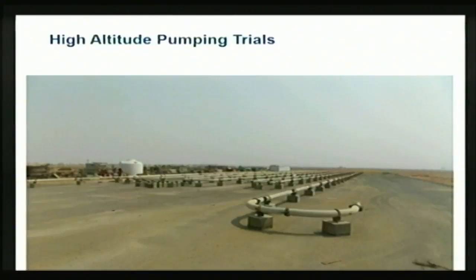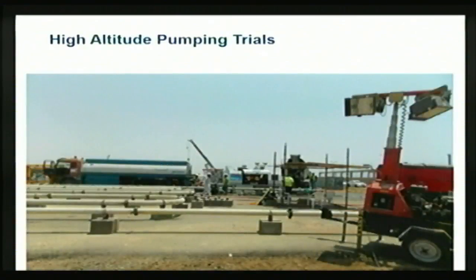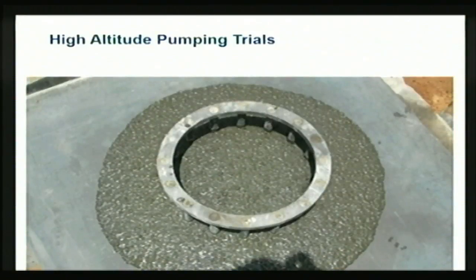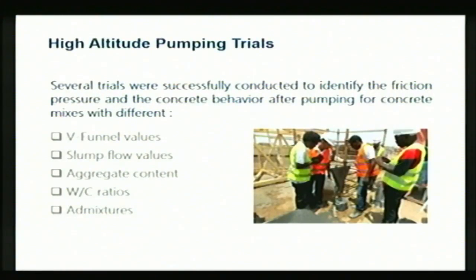Each elbow was 1 bar, each flange was half a bar, and we added that. So we designed that system to simulate even more than 500. This is the 1 kilometer that we did actually. And we did the high altitude pumping trials with the mix design that we finally decided on. And we started checking the J-ring and the stability and the slump flow and the V-funnel. All these were important. And we found out that on a height like this, the V-funnel becomes one of the key elements for pumpability. The V-funnel test becomes the real secret, whether this concrete is going to be pumped so high or not. So anything below 13 seconds was acceptable for us, but we found out that we actually needed 8 seconds to get the mix to reach there at the right flow.